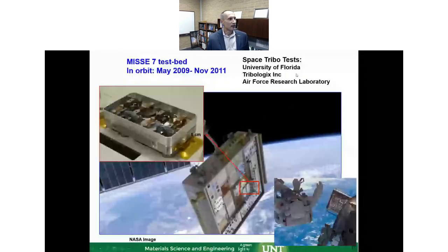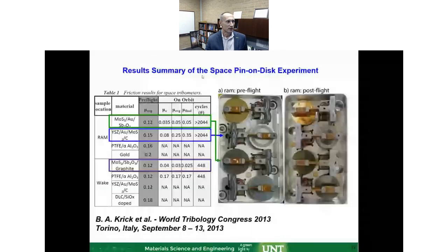So one of the very interesting and cool tests we did with University of Florida, Greg Sawyer, Brandon Krick, and others, and Tribologix, who provided some of these coatings. The Air Force Research Laboratory was, at that time, where I was working with them, and we were doing the experiment for the MISSE on the space station. And to our knowledge, it was the only tribological in-situ test performed in orbit. What you see here is actually tribometers built in boxes, which the astronauts take out and put outside of the space station, in front and in the back, for different exposure. They were left there while the tribometers were working and telemetering the data back to the ground, so we could see the friction coefficient in situ while it was going around the globe.